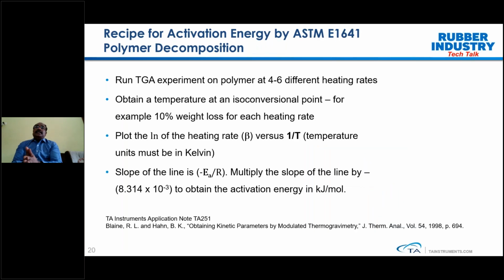What we do is capture the conversion rate, as per the ASTM technique, at 4 to 6 different heating rates, and then we plot the heating rates versus inverse of temperature. The slope gives the activation energy divided by the gas constant. That multiplied by the gas constant will give you the activation energy. So if you wish to understand the activation energy of your decomposition, basically you would be doing this kind of study actually.